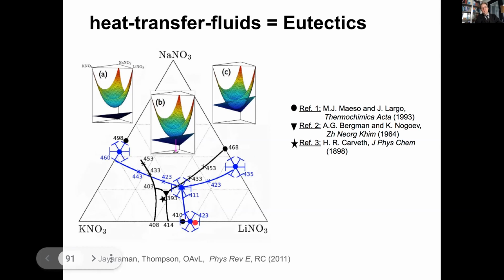But you see basically the eutectic for every combination of binaries, and the ternary prediction of the eutectic is here with 411 Kelvin. There are some experimental numbers, and they are shown here. These are experiments. Okay. And you see it looks similar, it's not identical, but it looks similar, and also the scale of the energies of the temperatures looks similar. So this is an illustration how you can use alchemy, for example, to rapidly identify in compound space combinations of